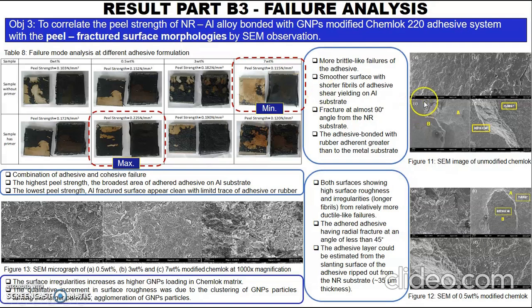Let's compare the SE image between figure 11 and figure 12. Figure 11 is the SE image of unmodified Chemlok. You can see that it has a smoother surface with short fibrils of adhesive, shear yielding on the aluminum substrate, while figure 12 shows both surfaces with high surface roughness and irregularities, and longer fibrils from a relatively more ductile-like failure. So this proves that the rougher the surface, the harder to debond, and it needs higher energy to split the rubber from the metal substrate.